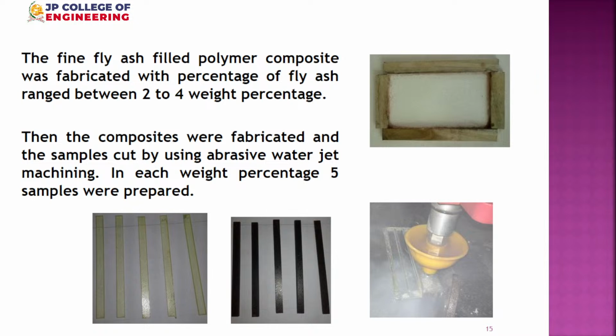Once it is ready, the top picture shows a mold in which the mixed resin is poured, and then you get a thick sheet-like thing, like cardboard. Then it should be cut. Cutting should not be done with a hacksaw because the edges will be broken, and then subsequent tests like flexural strength or tensile strength will not give good results. Therefore, go for cutting as in the bottom picture, using an abrasive water jet, and we obtain the strip specimens shown there. The white specimens are without fly ash, and the gray or black ones are with added fly ash. So we cut the strips, then took them for further testing.